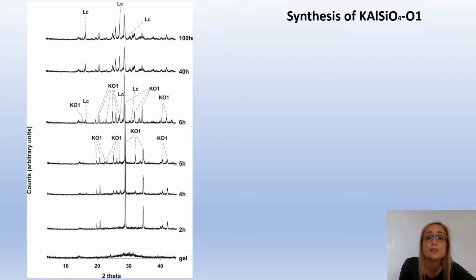The crystallization of the synthetic KAlSiO4-O1 phase is evident within the time interval 2–5 hours. After this time, the presence of KAlSiO4-O1 is associated with that of leucite in the time interval 6–100 hours. The experimental run ends with the final overlapping of the two phases.